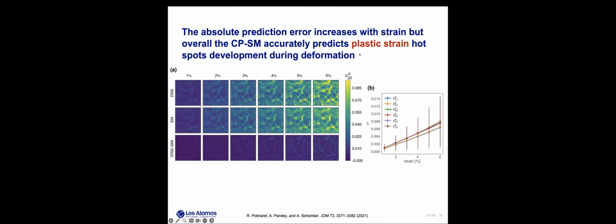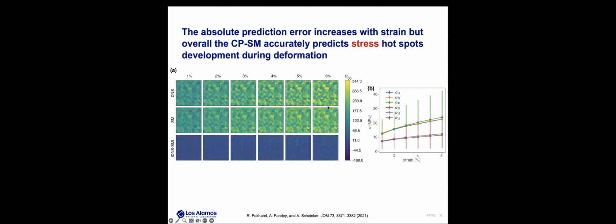I'm showing you the plastic strain component. Again, you can see that the model does a really good job in capturing these local hotspots and also the stress fields. And again, same results where we see the model able to capture these local hotspots in the micromechanical field evolution. And in this case, the error that accumulates at 6% is around 10%.